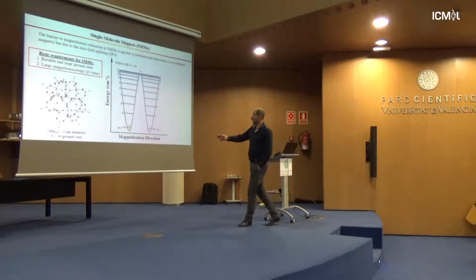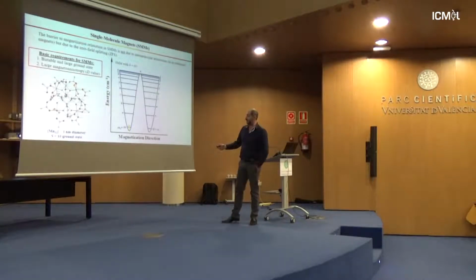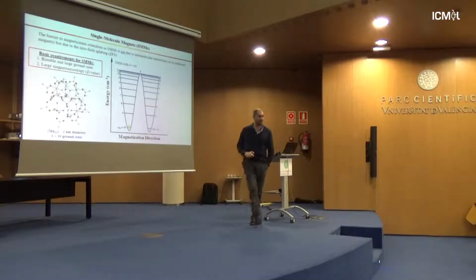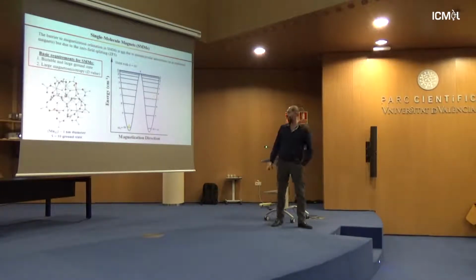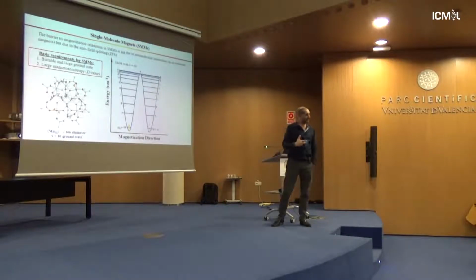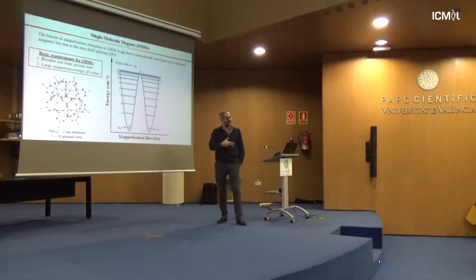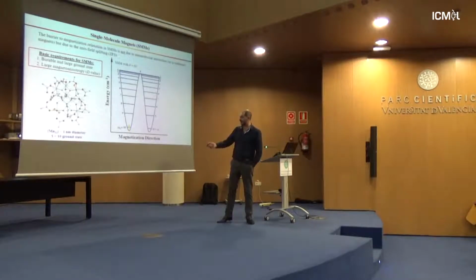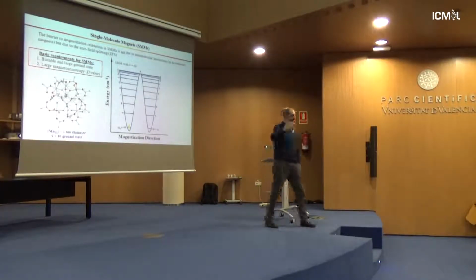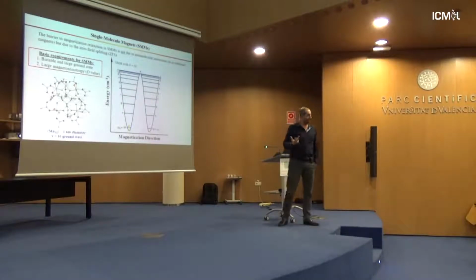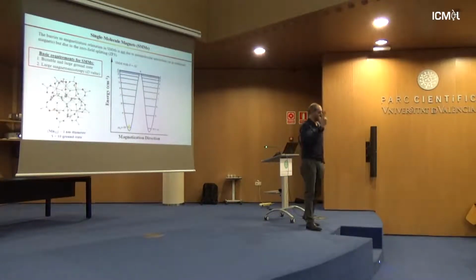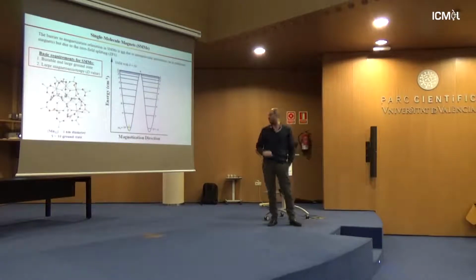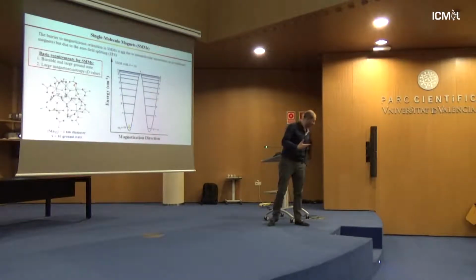Now returning to the double well that we can see and the different MS values. Those MS levels, as we call them, the microstates, are separated by a barrier which has a height of U. We call that the energy barrier. Why is it important? Practically and theoretically, you can store magnetic information in any of these levels. Of course, the magnetization or the spin has to relax. It cannot stay there forever. It takes some time to relax, or it can relax very fast in the majority of cases.